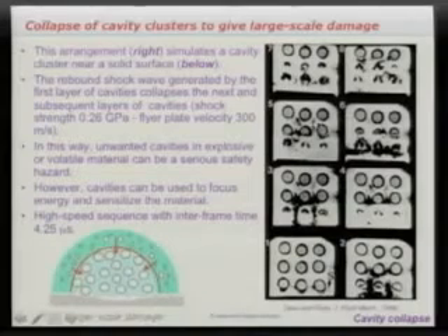cavity. Of course, our interest was really to try and explain why, when you look at damage on a subject like a propeller blade or some other component, often the damage is large scale, much bigger than a single cavity. And so we developed this approach to try and understand how cavities collapse in arrays. And so you can see here an experiment where we've got effectively a rectangular array of cavities, and you can see the shock passing up through this layer, and it collapses one layer first and then subsequently collapses other layers. And if you imagine a hemispherical cloud of cavities, you can imagine how the shock could then focus towards the center and produce this region of damage at the center here, bigger, much bigger than a single cavity.